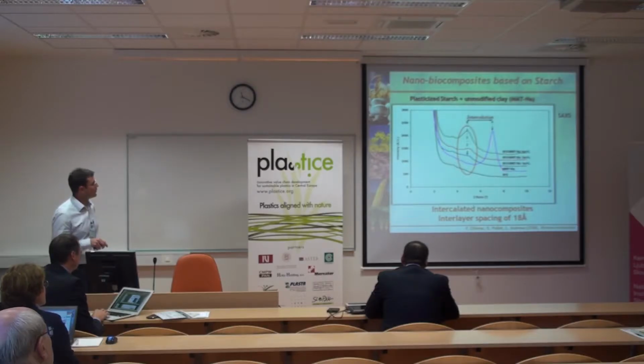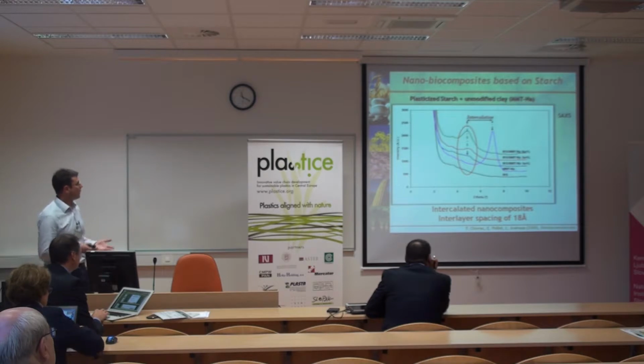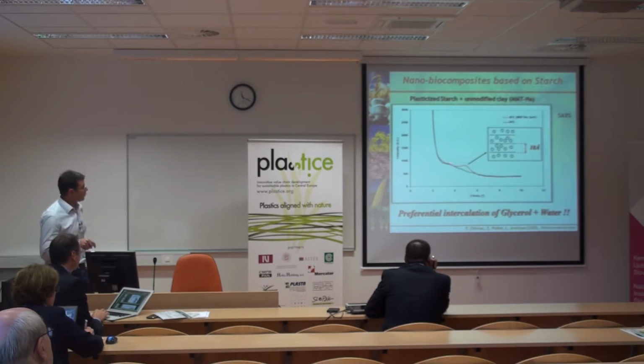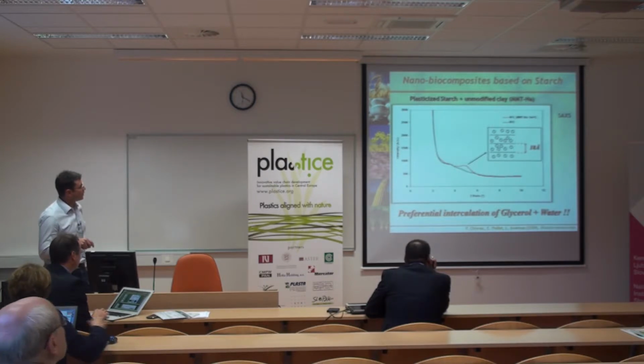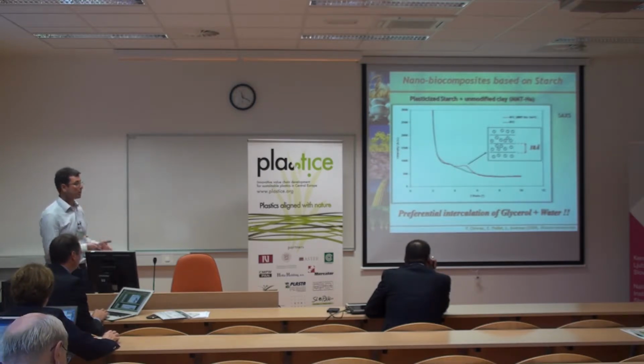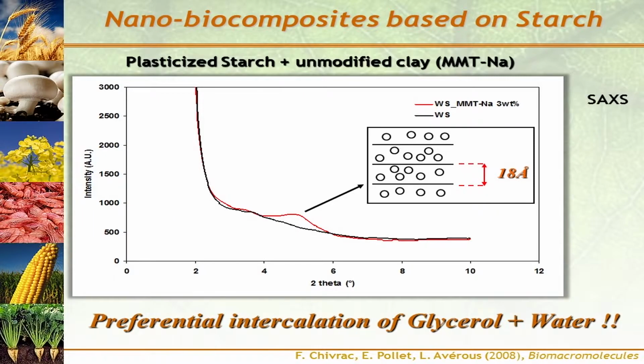You have an increase of the interlayer spacing, from about 12 angstrom in the neat clay up to 18 angstrom. So we have intercalated something between the clay platelets, but when looking into details, we have shown that it's only intercalation of water and glycerol molecules between the clay platelets, because we have this typical diffraction peak at 18 angstrom. So with non-modified clay, which is hydrophilic but does not show good compatibility with starch chains, starch chains are not able to intercalate the clay platelets because you have preferential intercalation of glycerol and water molecules.